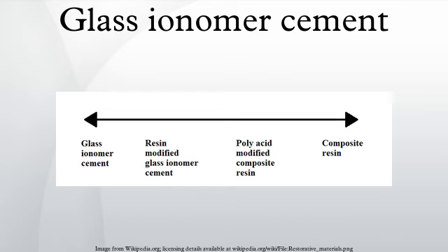Also, as the initial calcium crosslinks are replaced by aluminium crosslinks, most sodium and fluoride ions do not participate in the cross-linking of the cement. However, some sodium ions may replace the hydrogen ions of carboxylic groups, whereas the remaining ions are dispersed uniformly within the set cement along with fluoride ions.